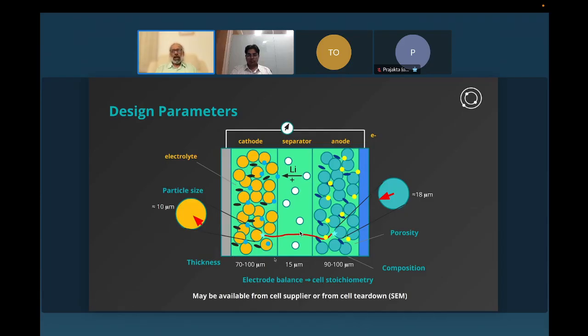The cathode can vary anywhere between 70 to 100 micron. The separator, which is much thinner than the anode or the cathode, is 15 micron. And the anode, typically for a graphite anode, is somewhere between 90 to 100 micron. So the thickness of the three components, the cathode, separator, and the anode, are examples of design parameters. We need to know them.